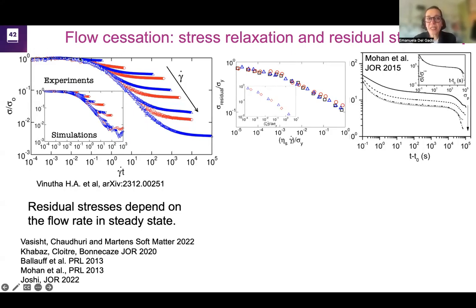And so what you see here is the relaxation of the stresses divided by the initial stress and plotted as a function of the time times the rate at which the system was flowing. So you can really see that this relaxation, in fact, depends on the rate at which the system is flowing. So when I stop the flow, there is a memory of what the system was doing before stopping the flow.